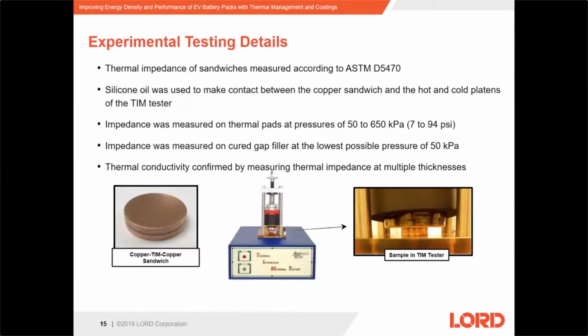For this experiment, we used an ASTM D5470 certified TIM tester from Analysis Tech. This piece of equipment functions by calculating thermal conductivity after measuring thermal impedance. First, the thermal impedance of the copper discs was calculated, and then the resistance of the interface between the copper substrates was calculated. This was done at different pressures and using a 200 centistoke silicone fluid as the medium to wet out the surfaces. Once these values were known, the thermal impedances of the thermal pads and gap fillers were calculated by finding the impedance of the whole system and then subtracting the known impedance of the copper and copper interfaces. This thermal impedance was measured over a range of pressures for the thermal pads, but since the gap fillers do not need pressure to be applied, the gap fillers were measured at the lowest possible pressure. From there, we calculated the thermal conductivity of the samples.